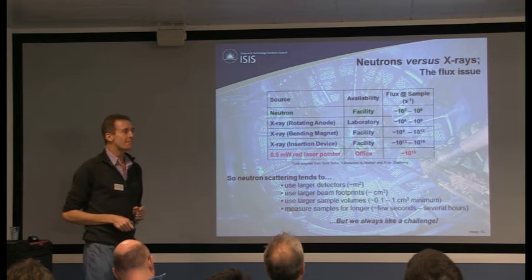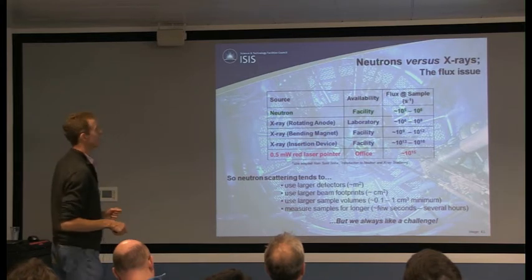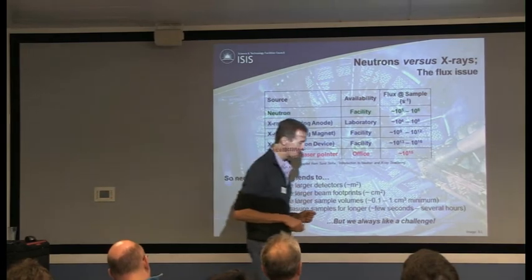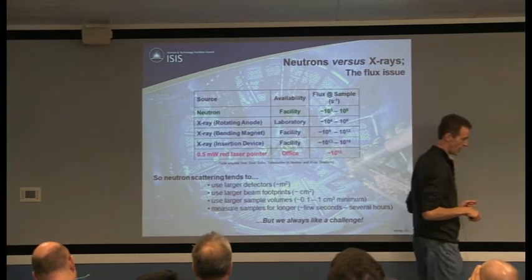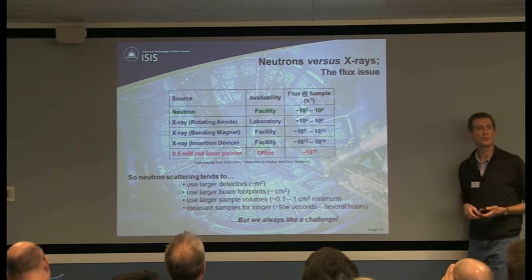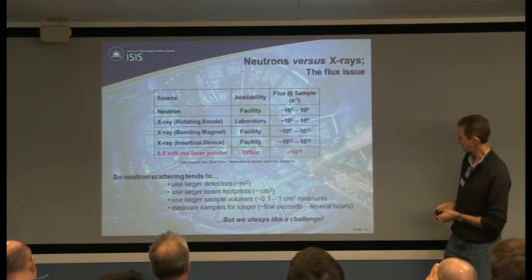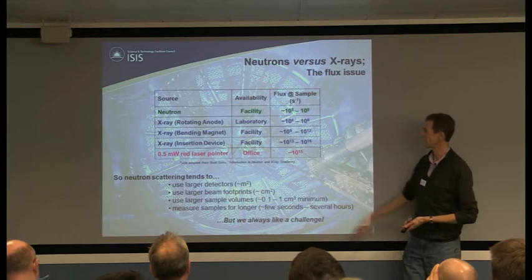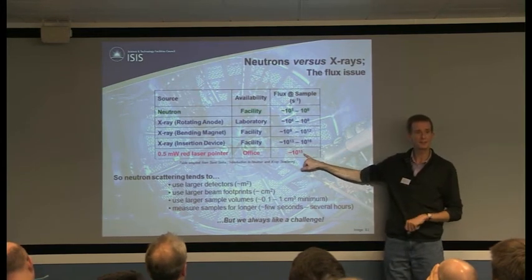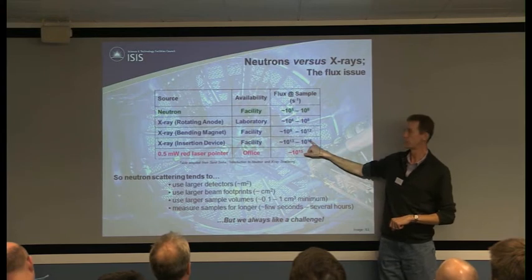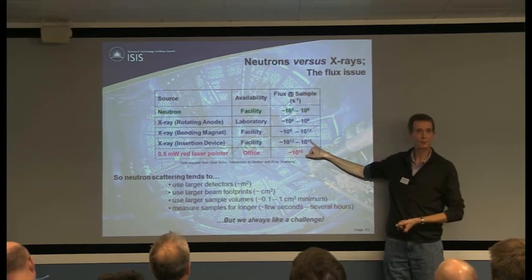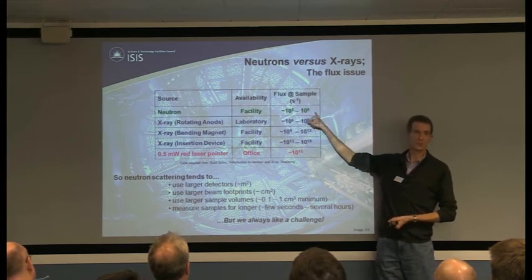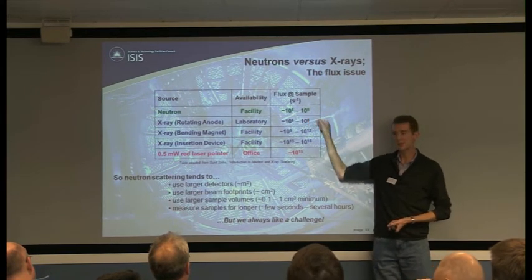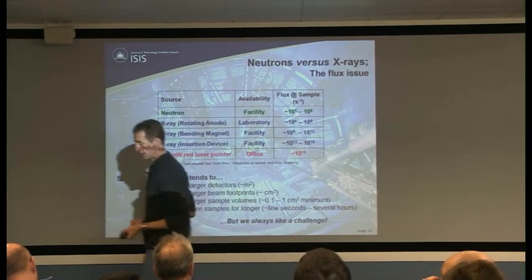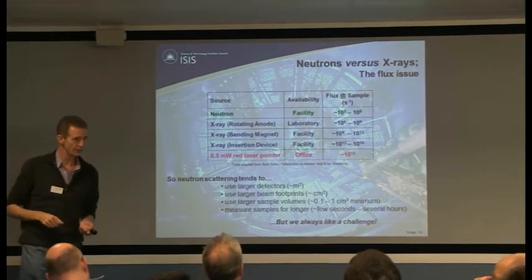But here's the but - there had to be a downside to all this, and the downside is that we cannot produce neutrons with the same sort of brilliance that you can produce photons. The laser pointer in here, for example, is probably producing something like 10 to the 15 photons a second, which is fairly comparable to the sort of X-ray photon brilliance of a diamond beamline. Unfortunately, with neutrons, we're several orders of magnitude down, so we can't do the very high time resolution experiments that you can do with X-rays.